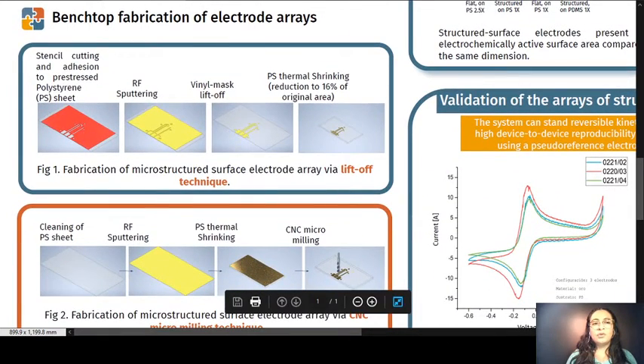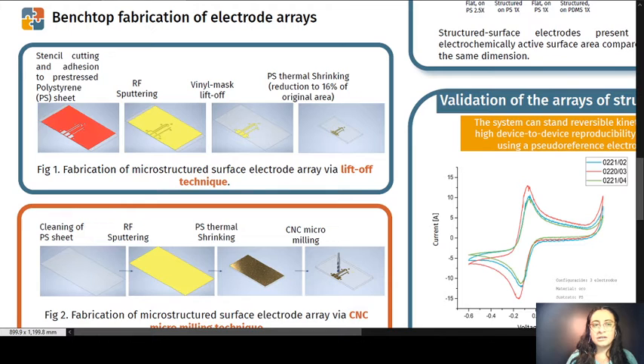We have developed two paths to fabricate such electrodes. Both start with a clean polystyrene pre-stressed sheet, and in the first one, we define the shape of the electrodes with a vinyl stencil, which is fabricated with a typical cutting plotter. Next, metal such as gold is deposited by sputtering, and the vinyl mask is lifted off. Finally, the device is introduced into an oven at 130 degrees to induce the polystyrene thermal shrinking.